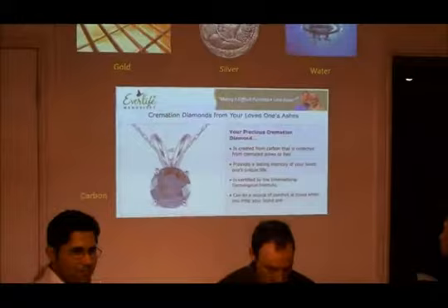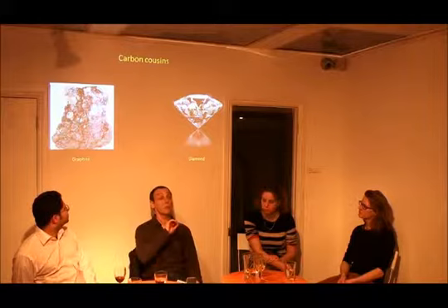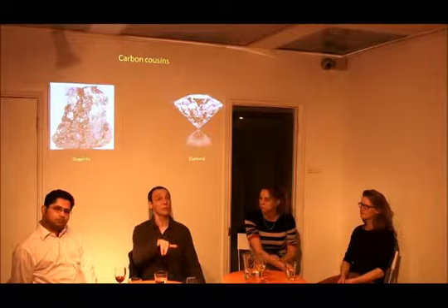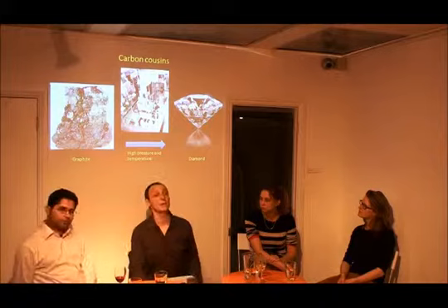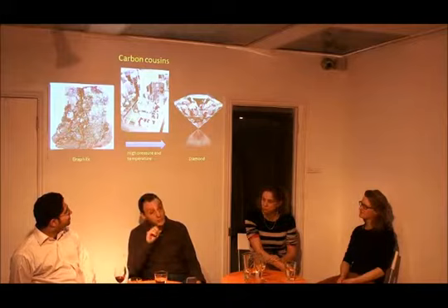Diamond and graphite are both forms of carbon, and they're often called the carbon cousins, because they're both pure carbon and they can be interconverted one to another. In fact, the first time diamonds were made artificially, and this was something that as soon as the chemical relationship between graphite and diamond was discovered, people were understandably very keen to try to do, it wasn't achieved until the 1950s, and it was done by squeezing graphite to tremendous pressures and at high temperatures in this huge press at the General Electric labs in Schenectady.